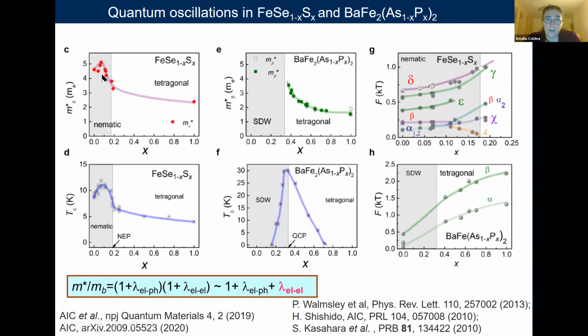And so what can we learn from here? Well, we learned that, indeed, in the presence of magnetic fluctuations, the effective masses are enhanced approaching this quantum critical point, and Tc has a strong enhancement. But in the case of the system where nematic fluctuations are supposed to be in the driving seat, we do not see a mass enhancement, and we do not see an enhanced Tc.